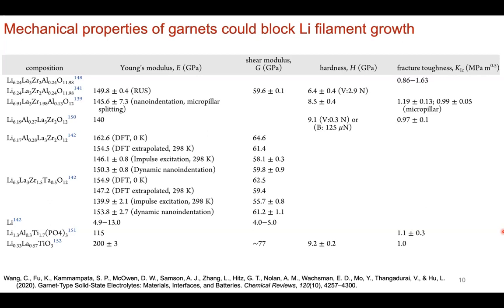And so when I take a look at this, I think, okay, there's a range. Obviously, the order of magnitude is similar. We're talking about 100 gigapascal or so. That's still more significant than something that is very soft, like lithium at 5 or 10 gigapascal, right? So it's good enough for understanding some fundamental processes.